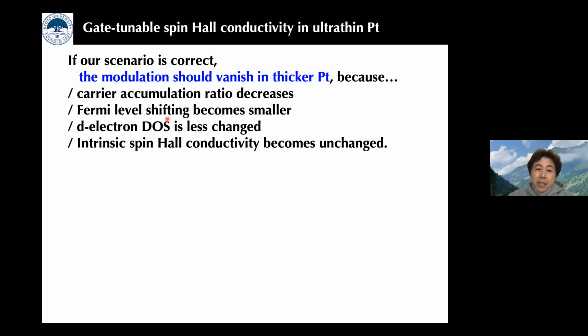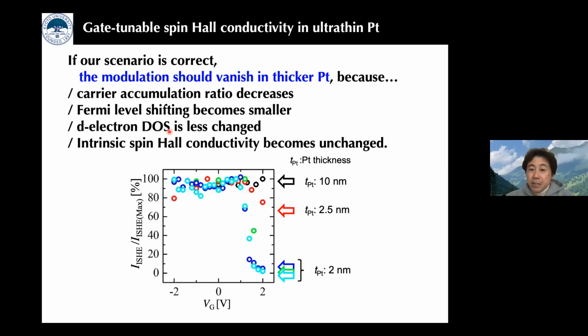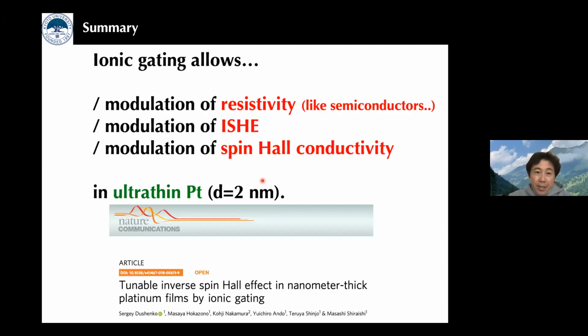But if Fermi level shifting does not take place, the density of states change is very small, and this suppresses the control of spin Hall and inverse spin Hall effects. In fact, when we increase the thickness of the platinum film, the effect rapidly diminishes, and this is strong supporting evidence that our understanding is correct. So this is a summary of the first topic. We controlled the resistivity, inverse spin Hall effect, and the spin Hall conductivity of ultrathin platinum by using the ionic gating technique.